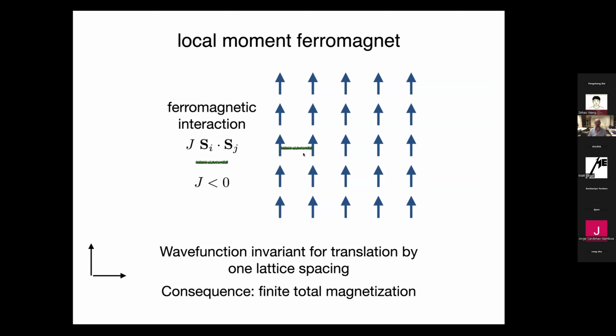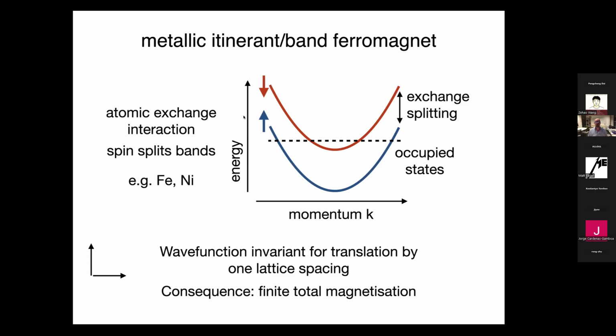I mentioned this two-dimensional square lattice where there's an interaction between nearest neighbors. The exchange constant is smaller than 0. I have a Heisenberg model, and the spins orient parallel. Now I know that the wave function in this case is invariant for translation by one lattice spacing. It's obvious. And as a consequence, one finds that this system will have a total magnetization, because there's a magnetization on one site that is copied to all the other sites, and therefore there's a net magnetization. If I don't look at a local moment ferromagnet, but at a metallic or itinerant band ferromagnet, the situation is similar. Now I have bands, and the up band is at a different energy from the down band.